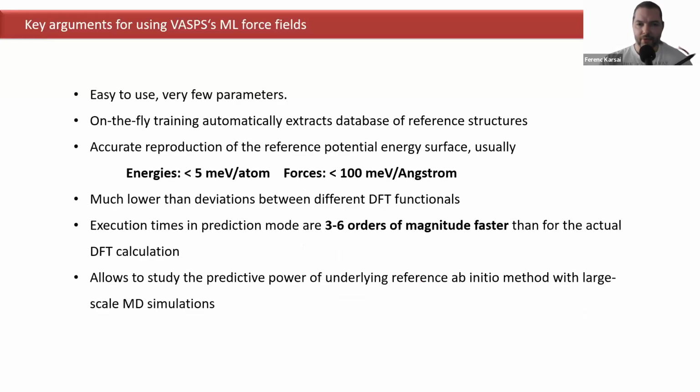Next, it has on-the-fly training, which automatically extracts the database and reference structures. Next, it's accurate. It's an accurate force field which can typically get you energy errors below 5 meV per atom and 100 meV per angstrom for the forces. And this deviation is usually much lower than between different DFT functionals.